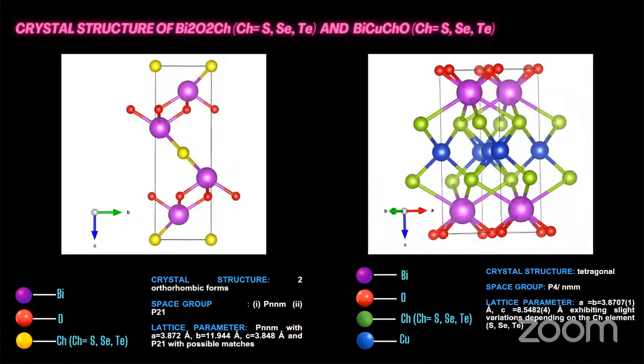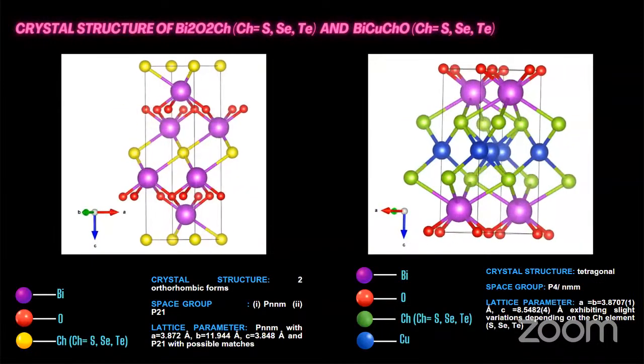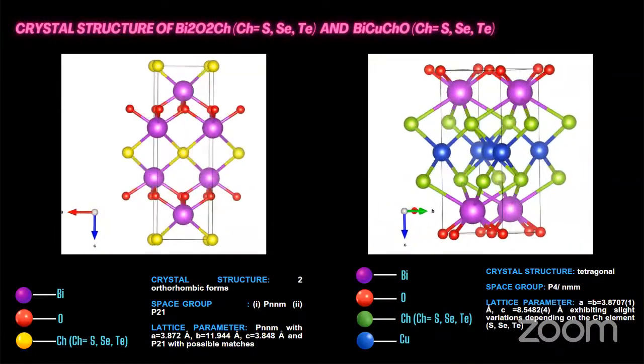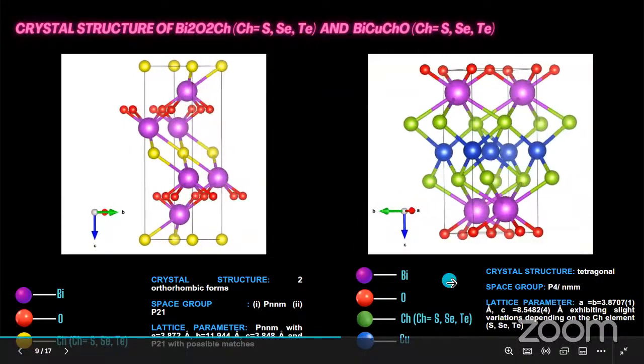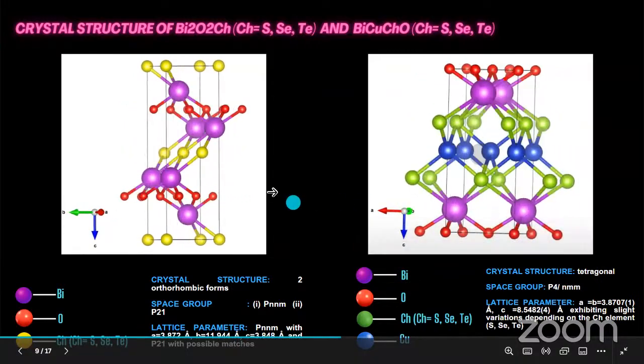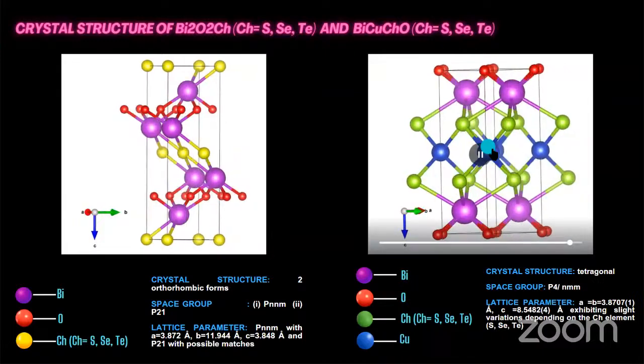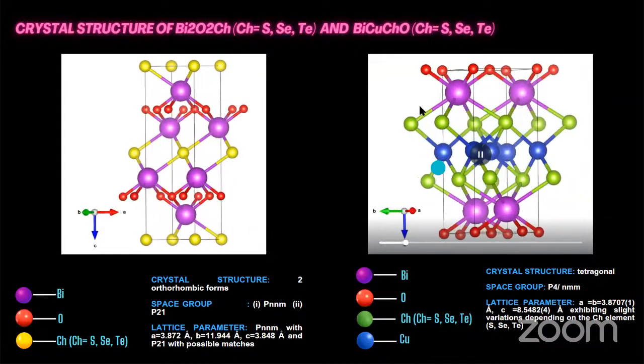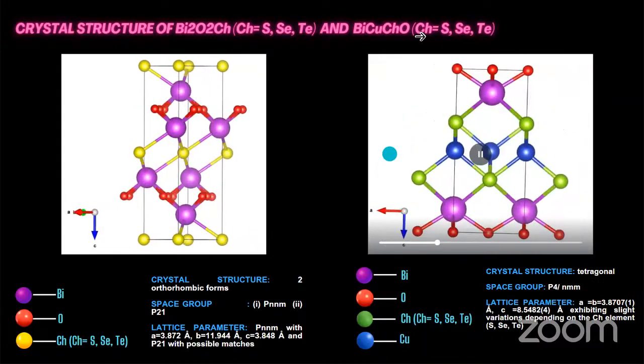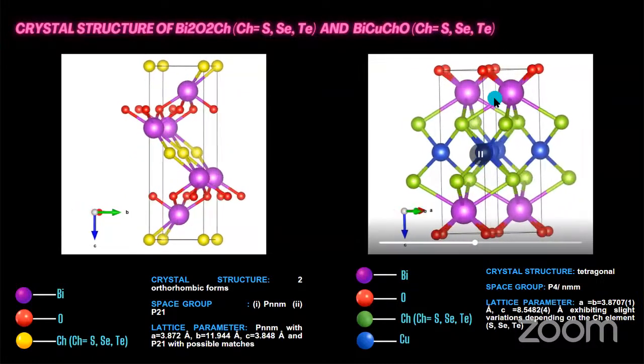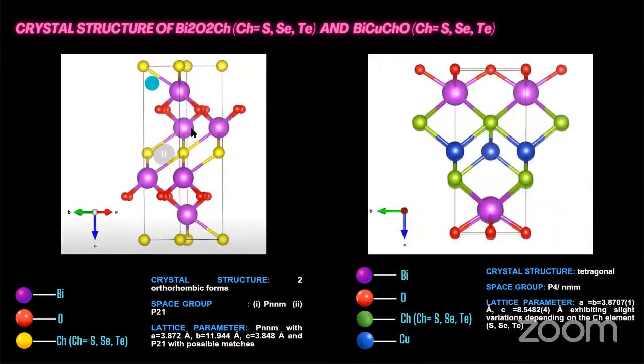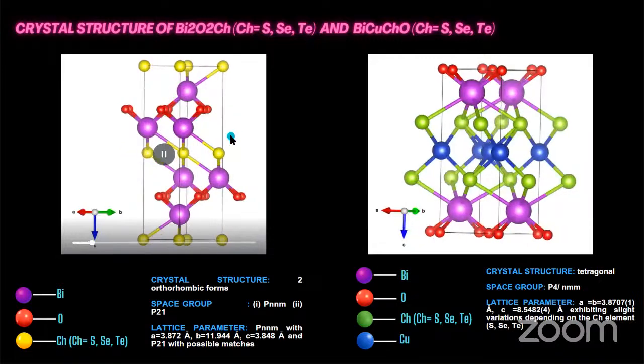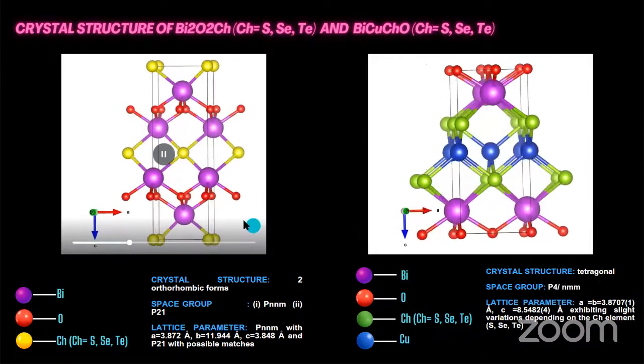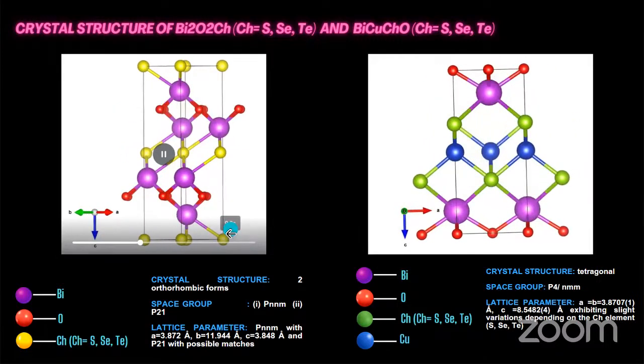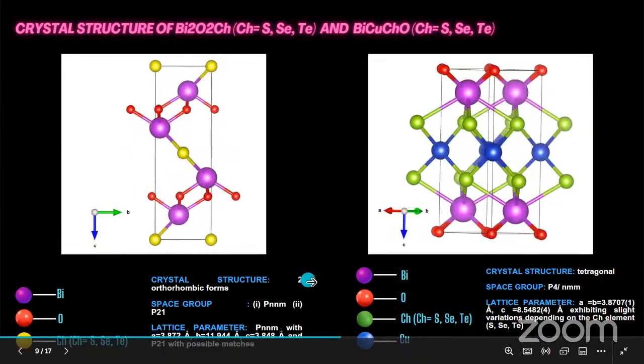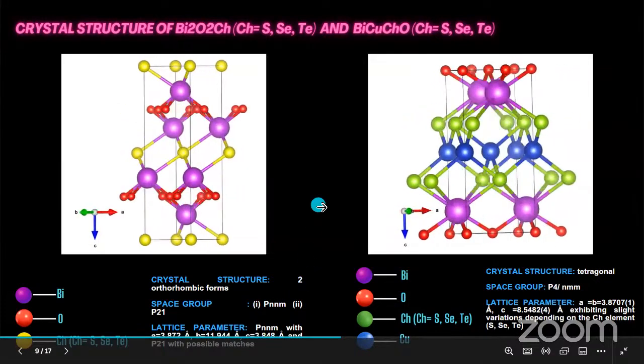Crystal structure of bismuth oxide chalcogenates and bismuth copper oxide chalcogenate materials. This slide depicts the crystal structure of two different materials, bismuth oxide chalcogenates and bismuth copper oxide chalcogenate materials. The image displayed here shows the tetragonal crystal structure of bismuth copper oxide chalcogenates and the orthorhombic crystal structure of bismuth oxide chalcogenates, which have lattice parameters with slight variations depending upon the specific element occupying the chalcogen's position.